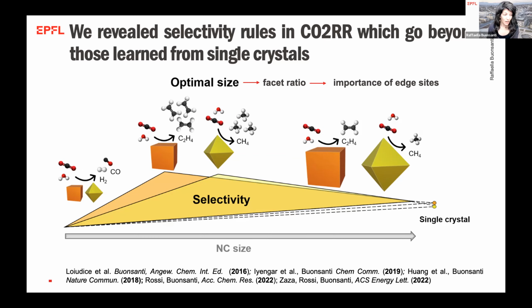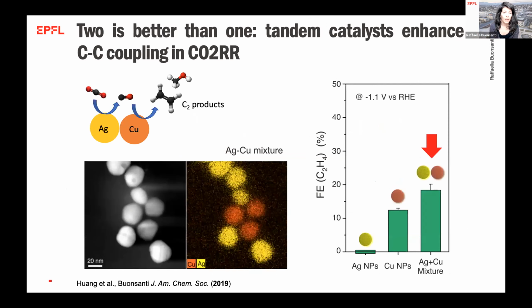Now, copper is quite unique. However, it also suffers from some limitations, and there is a lot of interest in the field in looking for bimetallic structures. And to improve further the capacity of copper to form C-C bonds, one of the conventional combinations is to have copper coupled with a CO-generating domain. In this case, we started to combine copper nanocrystals with silver in what is referred to as a tandem scheme. In this tandem scheme, silver generates CO, and then the CO is converted to ethylene. And what we did here was a simple physical mixture where, because of this tandem effect, we could observe an increase in C-C coupling when we mix the two particles.